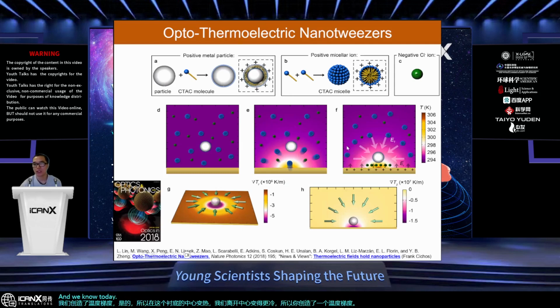And conventionally, we know thermophoresis will drive all the particles away from this hot region, away from this laser beam position. But the interesting phenomenon that happens is that the micelle moves faster and the ion moves slower. So as time goes on, there's a separation between the positive micelle and the negative ion. And we know this creates an electric field. And the particle has positive charge. So you can see that there's an electrostatic force, an electrical force, to trap the particle at this hot region. And that's the basic principle of optothermoelectric nanotweezers.